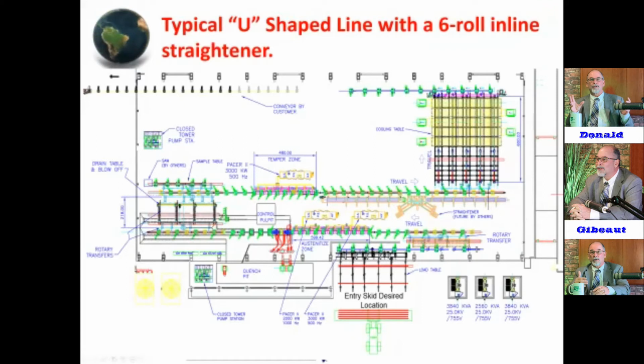But this is one of those systems where we were trying to fit it inside of a building. So we used a series of forced air convection fans. But again, they didn't begin until we hit down to about 600 degrees. Then they had a coating system over here somewhere, not shown in this picture. But again, we provided all of the transformers. This was from a 25 kV. But you can see the austenitize power again, 500 hertz below the magnetic Curie, 1000 hertz above, 500 hertz in this single temper system.